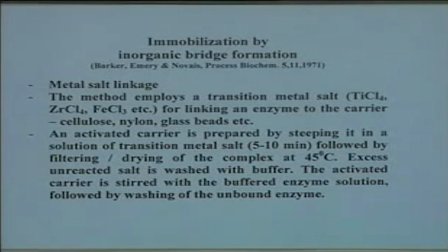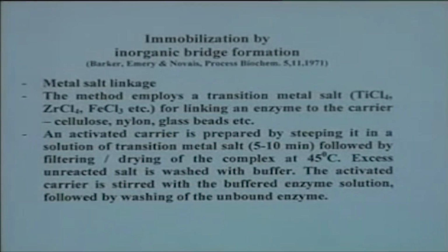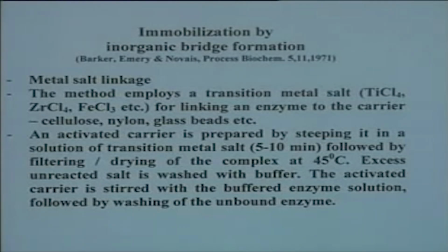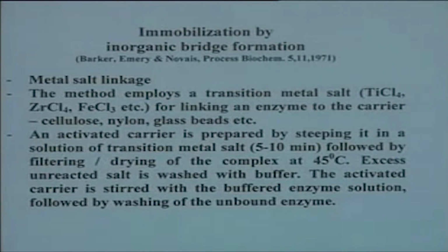I mention that it is important because a longer contact of the matrix in the transition salt solution can result in degradation, because the pH of these solutions, for example titanium tetrachloride, will be very low, almost 1 to 2, and if you put cellulose into it, it might get degraded totally.